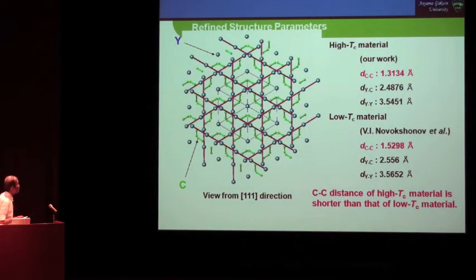This is a refined structure parameter looking at the 111 direction. The point is that carbon-carbon distance in the high-TC material is shorter than in the low-TC material, comparing these values, it is shorter and shorter.